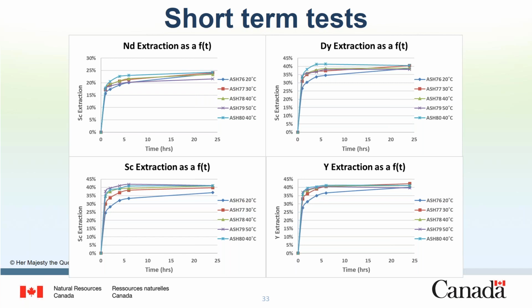It is unclear if the incomplete leaching of the REEs is a result of them being in different carrying phases or a result of incomplete liberation. Further testing is underway to elucidate the reason for these results. The rapid kinetics and the low activation energy suggest a low temperature process with a short solid retention time is suitable to leach a significant fraction of the REEs from this material.